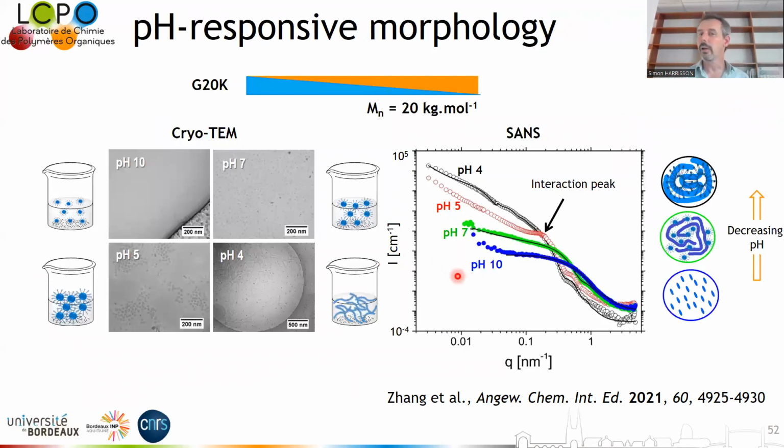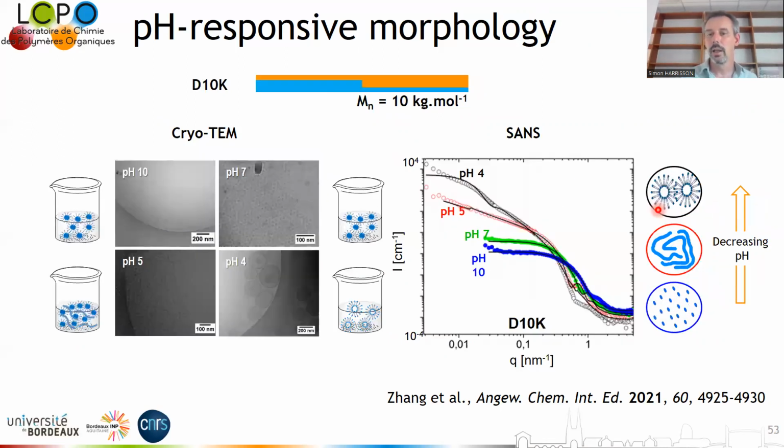And we also saw changes in morphology that were, again, very similar between the two types of polymers. So gradient copolymers passed from initially slightly elongated spherical particles through to worms at around pH 7 to pH 5, and then to a mixture of worms and vesicles, while our diblock copolymers showed similar types of behavior, again passing through these transitions of spherical to worm-like to vesicle type morphologies.